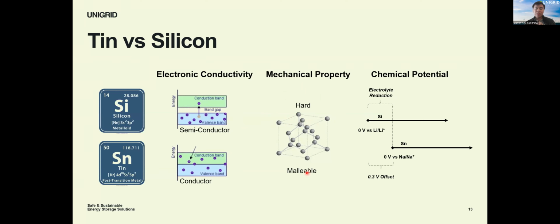Tin is very soft. Everyone has held tin foil before. Just using your finger to press it, it's going to deform. So it remains in contact with each other, and you can keep its expansion within its own pores at the electrode level. That's why it works very well in the cylindrical cell.